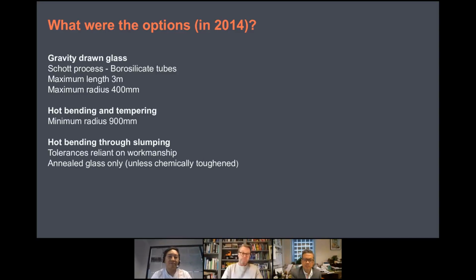So what are the options? Well, glass tubes have been around for some time. In fact, the very first glass tubes were made in the early 1900s by a process developed by Schott, really for the creation of experimental chemical tubes and for medical purposes, the idea of test tubes essentially, using borosilicate glass, a glass that has a very high tolerance to temperature. Now that process has developed, and of course the chemical industry has developed over the last 100 years or so, such that today, or at that point in 2014, the maximum diameter of a tube that you could achieve in borosilicate is about 400 millimeters. I've got the radius there, but it's actually the diameter, and the maximum length is about 3 meters.